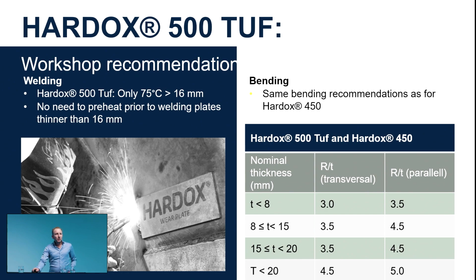A little bit about the workshop properties. First of all, welding. Welding is important for our steel, and we have tried to make this steel with the same good properties in the workshop as Hardox 450. If you look at welding properties of Hardox 500 Tuf, you don't need to preheat or change anything for material up to 16 millimeter. Above 16 millimeter thickness, we recommend a preheating temperature of 75 degrees, and that is not too high. And you don't need to change anything when it comes to welding consumables, compared to Hardox 450.